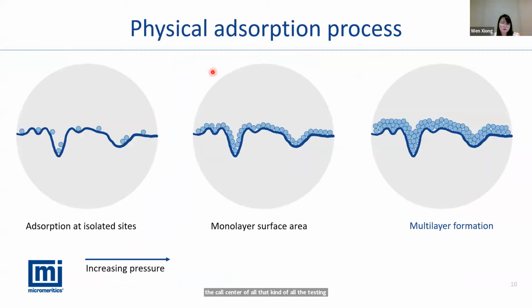In the physical adsorption process, we start testing the adsorption at very low temperature and very low pressure. At first, single molecules or atoms adsorb at some isolated sites on the surface. Then when we increase the pressure, we are able to see a monolayer of gas molecules attaching on the surface. And as we keep increasing the pressure, the gas molecules form multilayer adsorption on the surface.